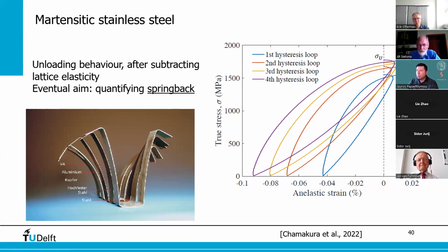And we did not manage to find a good equation for that yet. And I think the essential problem is that in the loading curve, we describe an equilibrium situation. We have two stresses, they should be the same, and that in the end results in the equation that we use. In the unloading part, it's not an equilibrium situation.